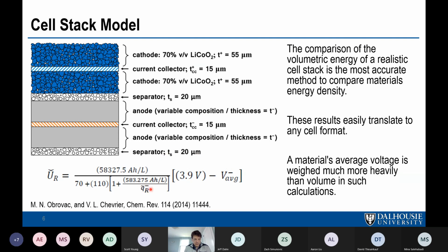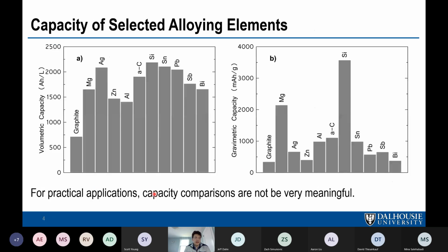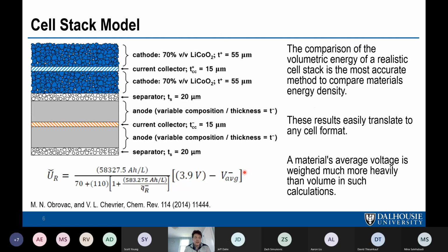Here in this equation, this Q tilde R minus is the volumetric reversible capacity of the negative electrode. And here, this is the average potential of the negative electrode versus lithium. And you could see by eye in this formula that this quantity, the volumetric energy density of the stack, is much more sensitive to the average voltage of the negative electrode than its volumetric capacity. And of course, also its gravimetric capacity. So you can see why, going back to these slides, that really this doesn't tell the full picture. It doesn't say the most important information, which is related to the potential of the negative electrode, which has the greatest impact on the volumetric energy density of the cell.